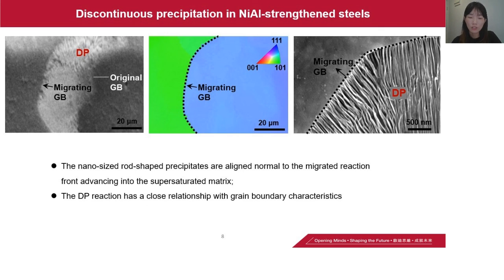We use EBSD to deeply understand the growth of these DP colonies. As we can see from the left two figures, the grain boundary migrates from right to left. And in the high magnification on the right, we can see that the nano-sized rod-shaped precipitates are aligned normal to the migrating reaction front, advancing into the supersaturated matrix. This kind of reaction has a close relationship with the grain boundary characteristics.